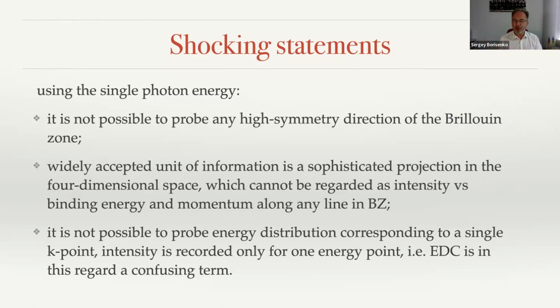And finally, it is not possible to probe the energy distribution corresponding to a single K point. Because, you can check it yourself, the very famous tutorials show that ARPES is an extension of XPS. You know XPS? XPS is an energy distribution. So ARPES is an extension of XPS, the same just for every K point, which is not correct. And this is the topic which I want to discuss with you, and how to avoid this confusion.